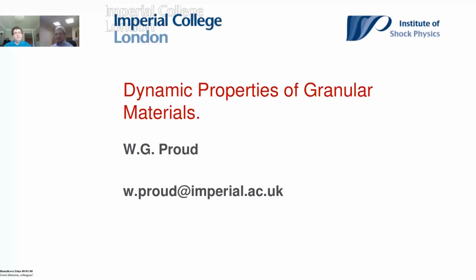Yeah, exactly. Because when you look at the low density silica dust, you see something which is effectively not a very good stress transmission system. So ultimately, the response never reaches the level of anything other than very dusty, low density material with compaction occurring, but it never gets to the point of having anything that we define as a kind of elastic precursor or strength term. It's just straightforward compaction. Whereas when you go to something with obviously between 95% porosity and 40% porosity, there's a very big change there. But when you get to 40% porosity, you can clearly see there are precursor waves in the system associated with rearrangement and fracture and the initial compaction of the system, followed by the very aggressive compaction of the system. So there is this transition in behavior.